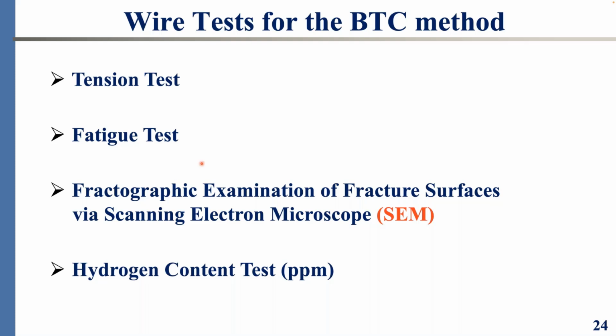And we do a hydrogen content test. We can speak later on, if there is time, about why we do it. But in a nutshell, we do the hydrogen content test using a fusion method in which the wire sample is heated to a very high temperature, so it melts into a molten state, and then the concentration of the evolved hydrogen gas is detected by thermal conductivity techniques and expressed in parts per million, thus the ppm.